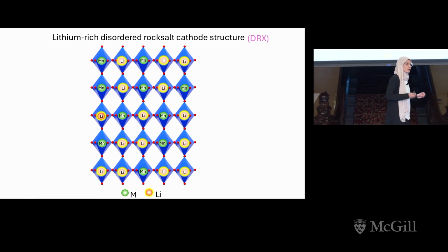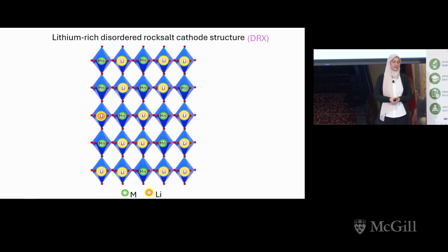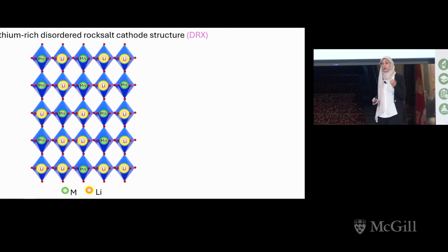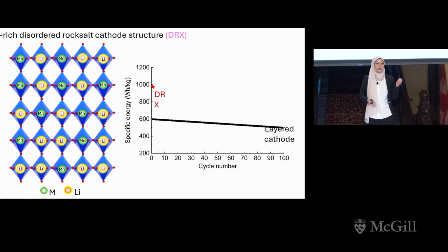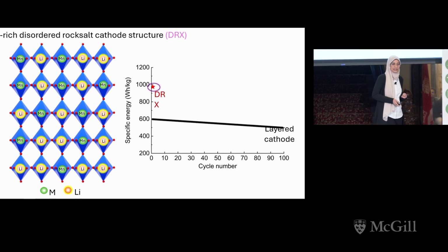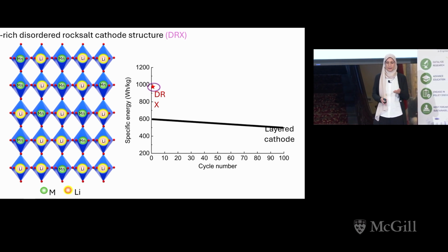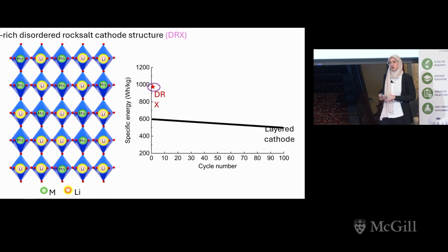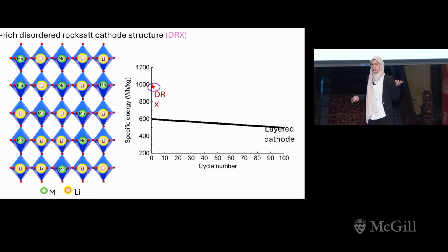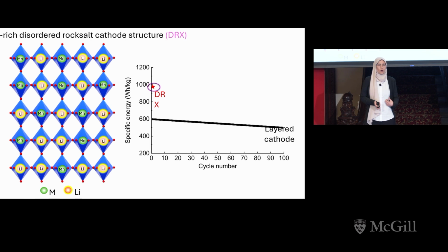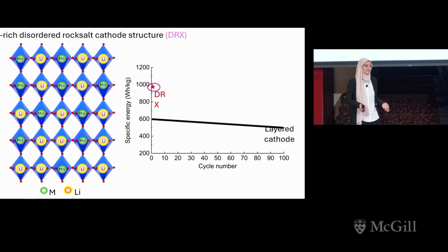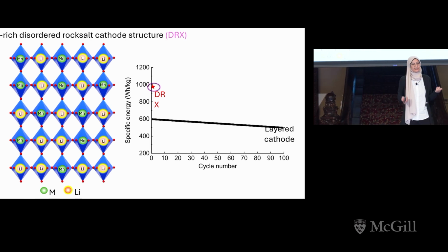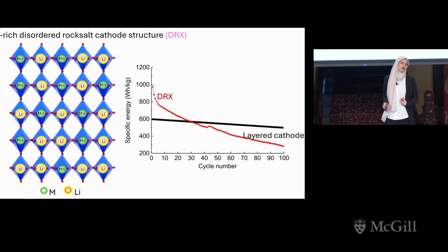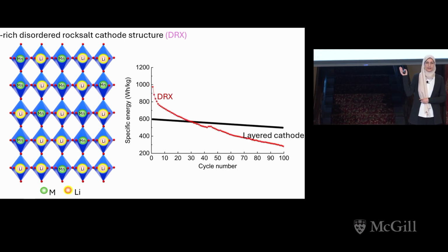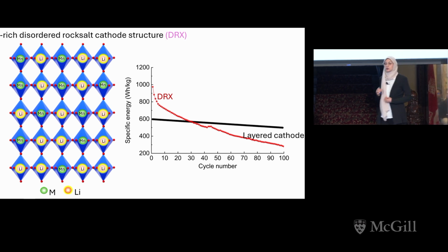So the question now is, why did I choose to work with this specific cathode material? Why DRX? Simply because with this material, we can get around 1,000 watt-hour per kilogram energy density, which is very high compared to the commercialized one. You might wonder, if this material is so good and can reach this high energy density, why is it not in our batteries yet? Simply because this high energy density doesn't last forever. It declines so quickly, as you can see with the red line. So in my PhD, I'm trying to solve this issue.